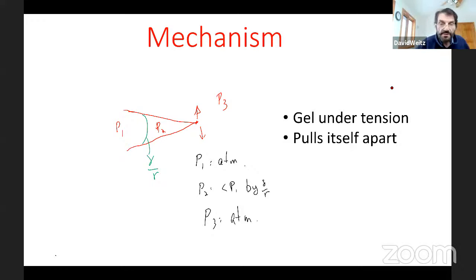So really what's happening, you can think of it this way, and I've just drawn this in a schematic way. This is the crack here. This is the tip of the crack. It's moving in this direction. This is either fluid being injected or air being injected. This is either at the injection pressure, so it'll be slightly higher than atmosphere, or if we're just injecting air, this is at atmosphere. And far away from the crack, it's also at atmosphere. So the pressure of the water, because of the Laplace pressure, is lower. So this is a low pressure regime.